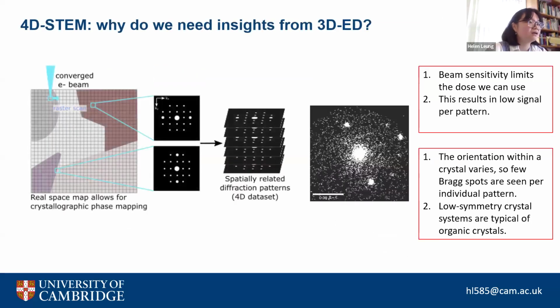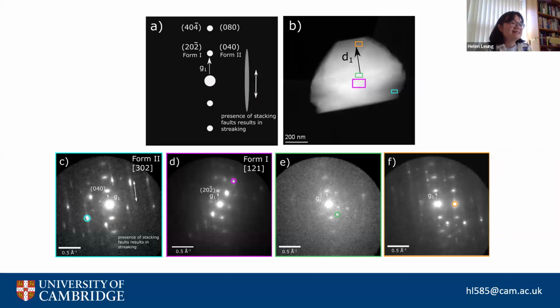So as I mentioned earlier, just working with the 4D STEM data alone is very, very difficult because of beam sensitivity limits and this basically low signal per pattern that we get. And so the experimental pattern I've got on this slide is quite typical of maybe something that we might get from 4D STEM. If you don't have any information about the structure you're working with, this is very difficult to work with in a very meaningful way, especially because in these organic systems, the symmetry is relatively low. So that means you might get at certain orientations very few Bragg spots seen per pattern. And this is exacerbated by the low symmetry.